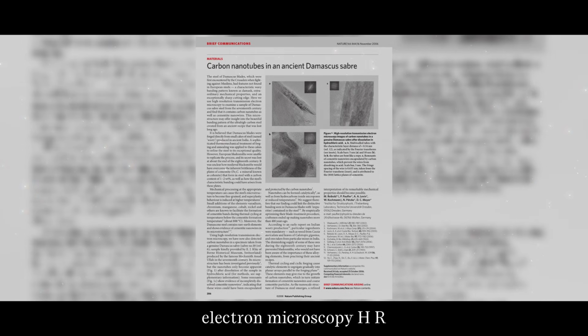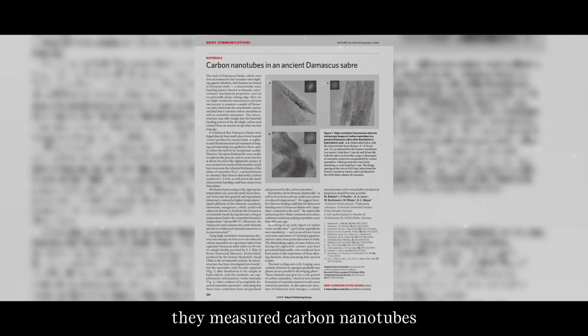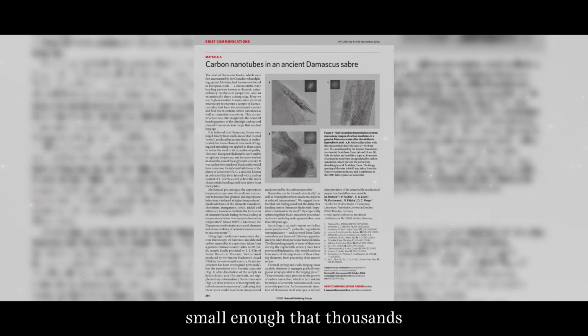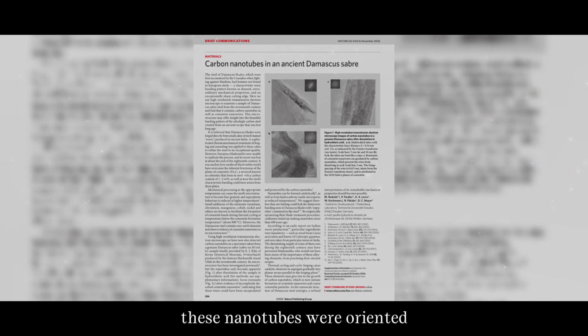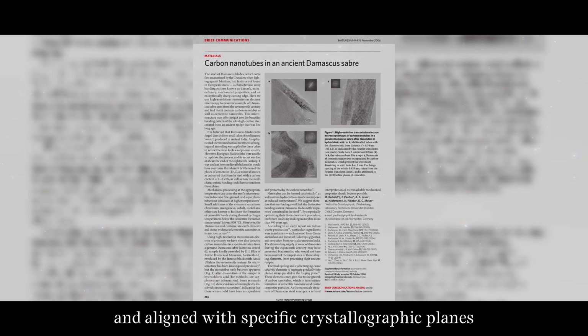The research team used high-resolution transmission electron microscopy, HRTEM, to image the nanostructures directly. They measured carbon nanotubes with diameters of 10 to 20 nanometers, small enough that thousands would fit across the width of a human hair. These nanotubes were oriented parallel to the carbide bands and aligned with specific crystallographic planes in the iron matrix.